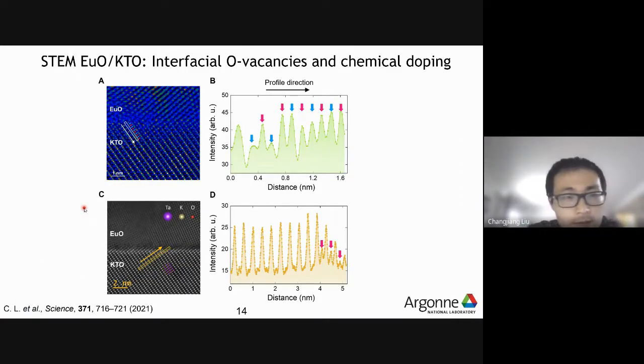So we did some further characterizations. For example, here on the top panel, we have the light image, STEM, which is very sensitive to light atoms such as oxygen. And we found that in the interfacial region, from left to right, this is the interfacial region, and this is the KTO substrate, which follows this arrow. You see that at the interfacial region, the oxygen intensity becomes lower. So that is suggesting that there are oxygen vacancies forming at the interface.